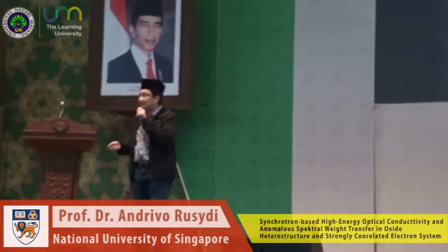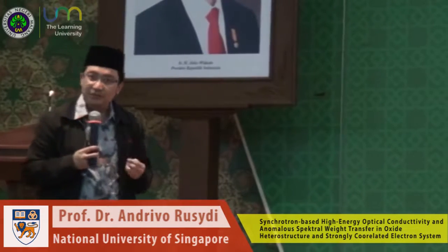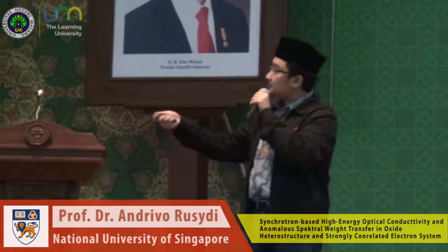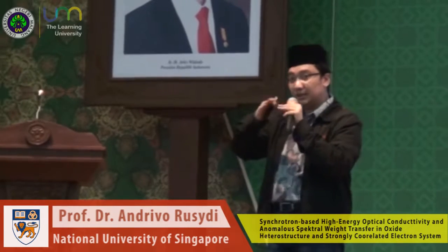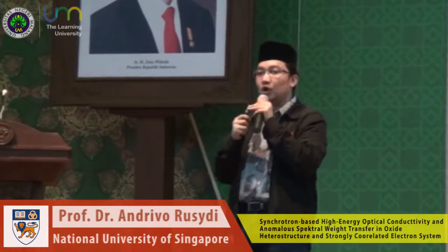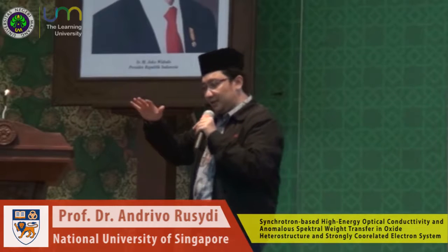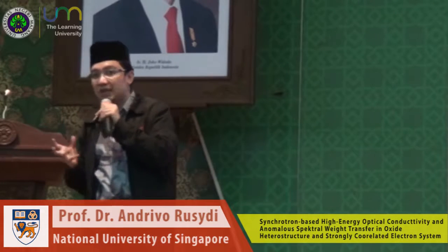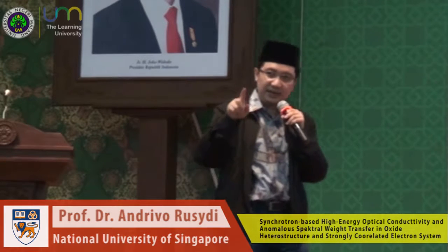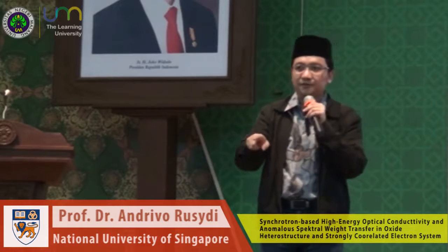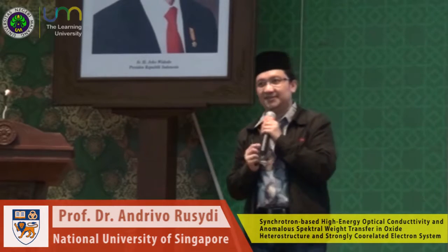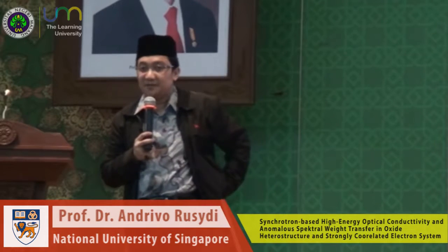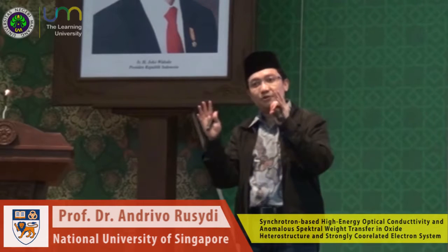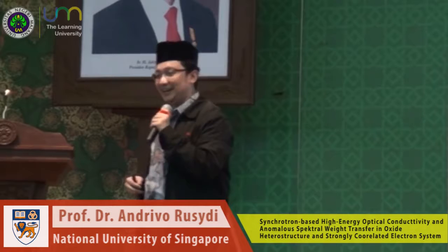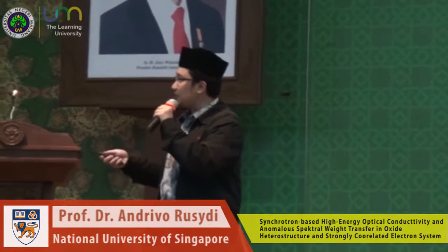This technique at the same time, we are also able to detect so-called vacancies, like the stoichiometry of your material. In this case, for 5, 6 unit cell and above, where the samples are metal, it turns out there are so-called oxygen vacancies. At the surface of LAO, the oxygen tends to be removed from the sample, and that releases an electron. And the electron from that surface goes toward the interface to compensate the polarization divergence. So it is a very interesting phenomenon in physics, and yet very simple to explain if you are able to measure the total number of electrons. And the same thing with other semiconductors, you can use the same technique too.